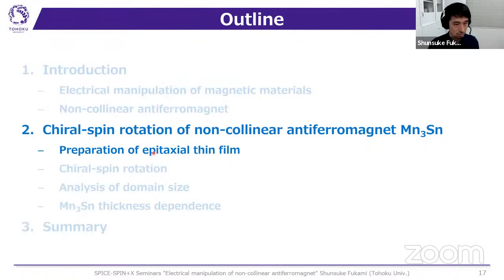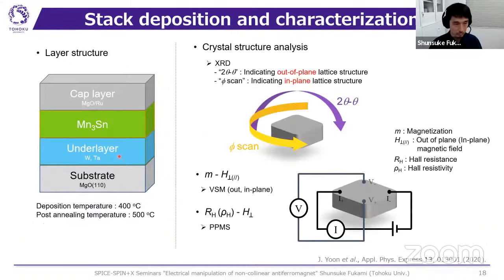Okay, so first I'd like to describe the preparation of the epitaxial bilayer structures. This shows the stack structures we studied. We used an MgO (110) substrate, and we tried several underlayer materials to grow the manganese-3 tin.